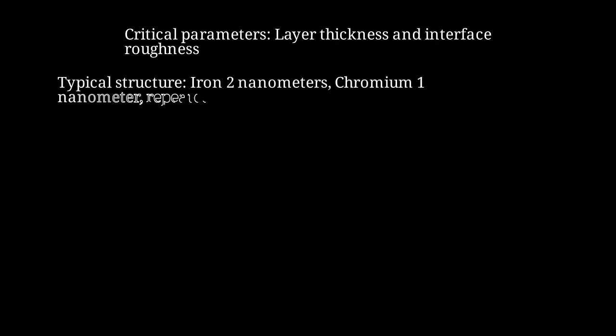A typical GMR structure might consist of iron layers 2 nanometers thick, chromium spacers 1 nanometer thick, repeated 20 to 50 times. The total stack thickness is only about 100 nanometers.